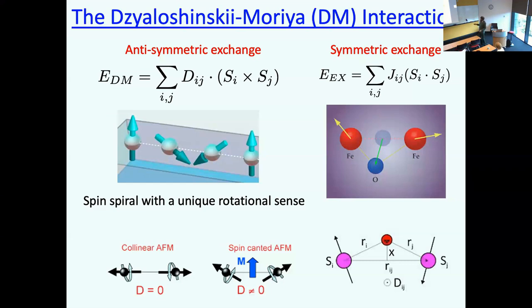Well, it's very useful in material science. It leads to non-collinear vector fields. That's what you saw in skyrmions. And if you have an antiferromagnet with no Dzyaloshinskii-Moriya interaction, that means they're collinear. They are tilted antiferromagnets. Antiferromagnets should not have any magnetization, but they do find in experiment residual magnetization. That's a consequence of Dzyaloshinskii-Moriya interaction.